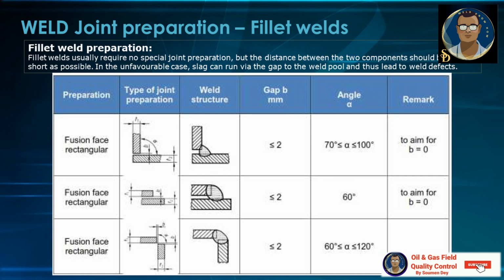Here are some fillet weld preparations in the table. Usually fillet welds don't require any special joint preparation, but the distance between the two components should be kept as short as possible. In the unfavorable case, slag can run via the gap to the weld pool and thus lead to the weld defect. The preparation of fillet weld.